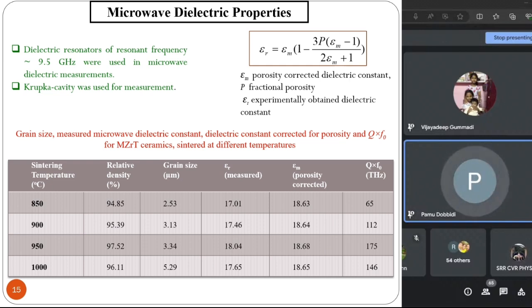So now, how is your material better than what is done in the literature? Now you see the relative density we have shown, sintered at 850, 900, 950, 1000 degrees C. At 950 degrees C, we got a density of about 97.5%, which is a very good density, with an average grain size of about 3.3 microns. And you look at the dielectric constant. This dielectric constant is measured at around 9 to 9.5 gigahertz. You see it given in the green letters.